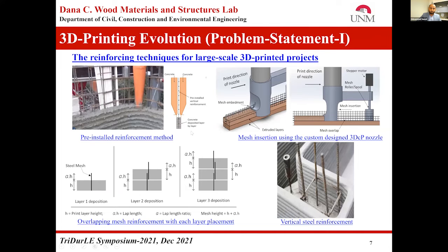Another big challenge is the reinforcement. Several researchers have used different approaches in 3D printed construction, including pre-installed reinforcement, post-installed reinforcement, and in-process reinforcement layers. And some of them have also used short fibers to reinforce the 3D printed concrete. But still, none of them is quite effective, because using all these approaches, the automation involved in 3D printing is disturbed, because we have to stop the printing process, and it can slow down the printing process also. And to lay down these reinforcing meshes, we need labor force also.